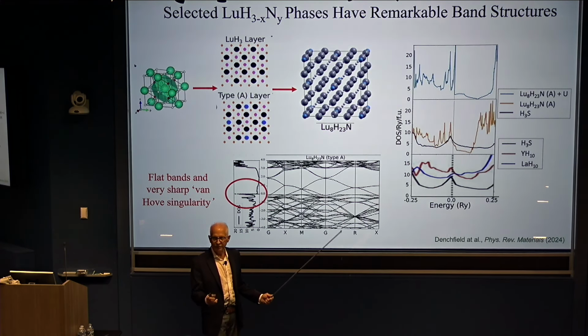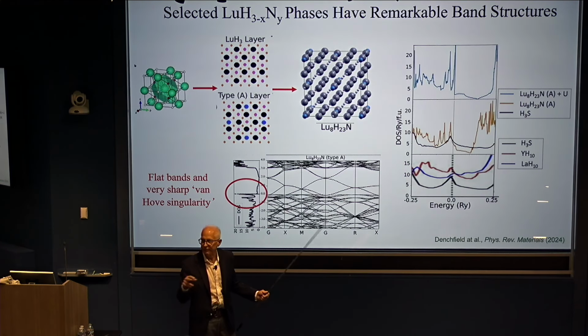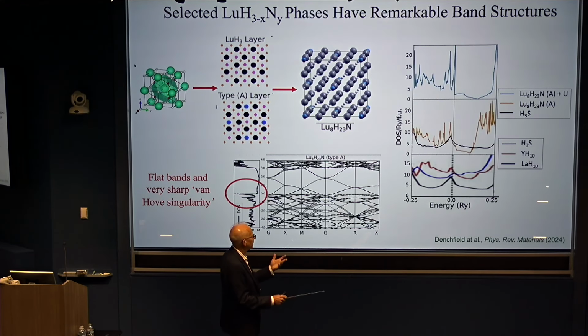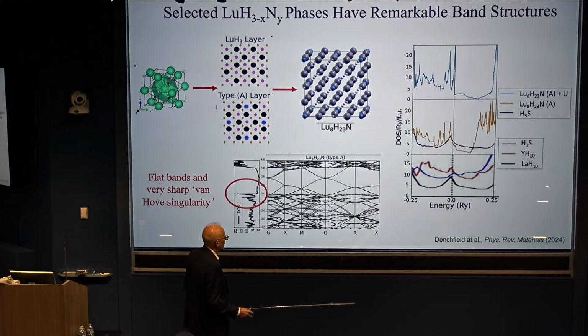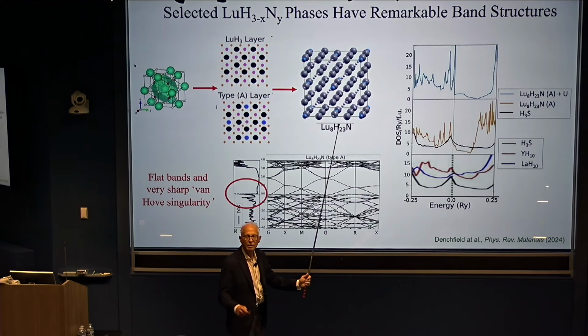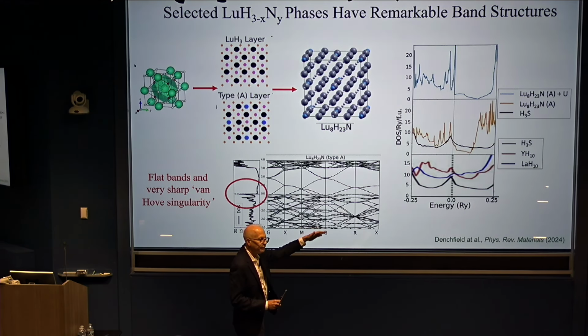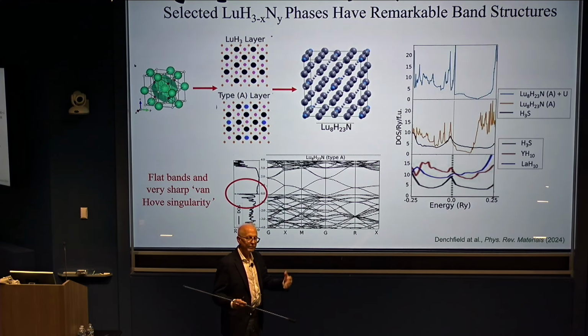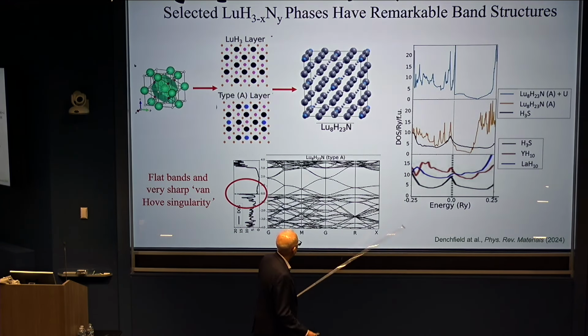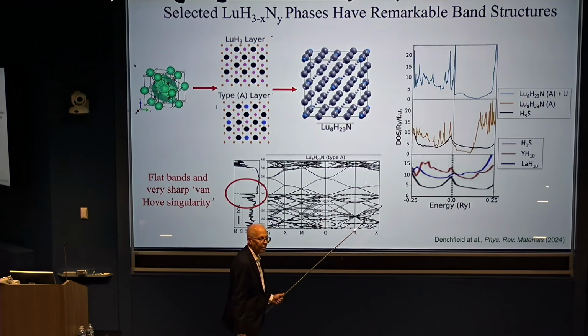These are very different materials than the superhydrides I talked about before, where you might have 10 hydrogens per metal. Here you have 2 to 3, depending on the stoichiometry. So is something different happening here? Well, what he did is he decided not to use a structure search method because he wanted to look for all the different possibilities you might have in terms of the electronic properties, not looking for the energy necessarily, looking for metastable phases, in fact, because the structure search approaches were not finding anything interesting. So he built basically crystal structures on a computer, sort of the old-fashioned way, and was able to find various combinations of layered structures that had really, really remarkable electronic properties.